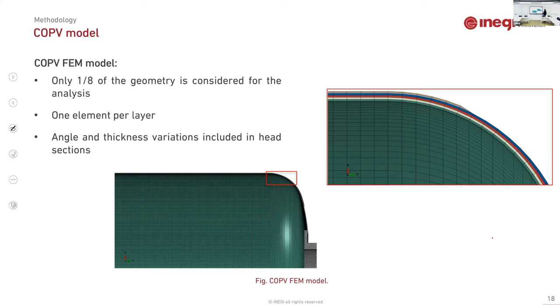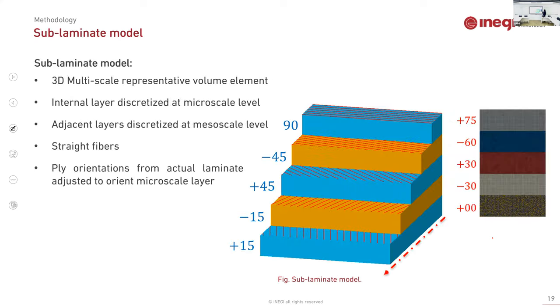And this vessel is modeled using 1/8 of the geometry. It is an approximation because the fibers are not exactly symmetric, but the model is acceptable for the sample that we want to do. I have considered one element per material layer, and the angle variation and the thickness in the heads is also considered to model this part. On the other hand, this is not a coupled model, this is a parallel application of the model. I also have introduced a sublaminate model.